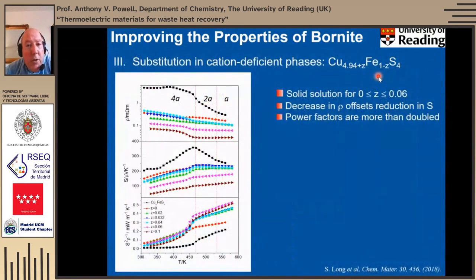So the final example I'll show is where we combined 2 strategies, is that we wanted to adjust the copper to iron ratio whilst also having some vacancies present. So this is no longer copper 5, this is copper 4.94. So we introduce some vacancies, we then adjust the copper to iron ratio. So once again, we see significant improvements in the electrical resistivity, which falls, which then feeds into quite large increases in power factors. Power factors are more than doubled here.